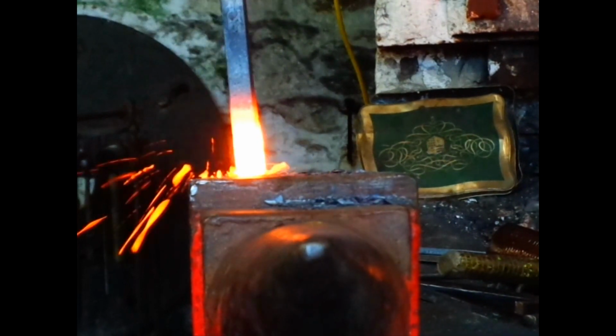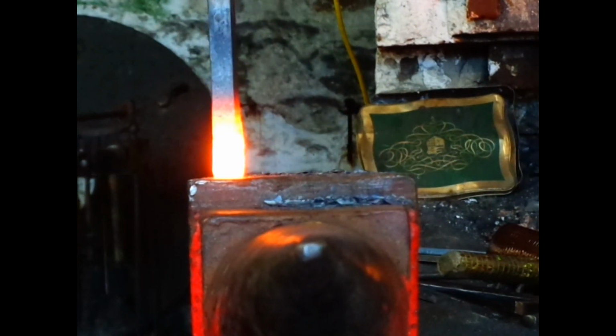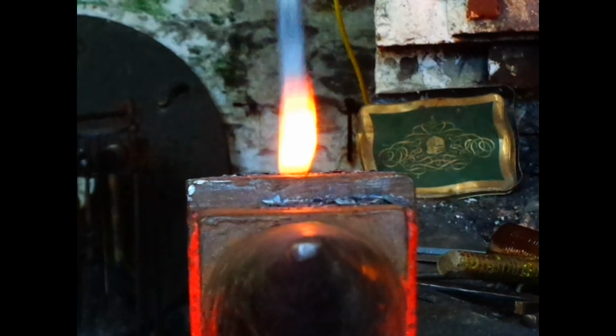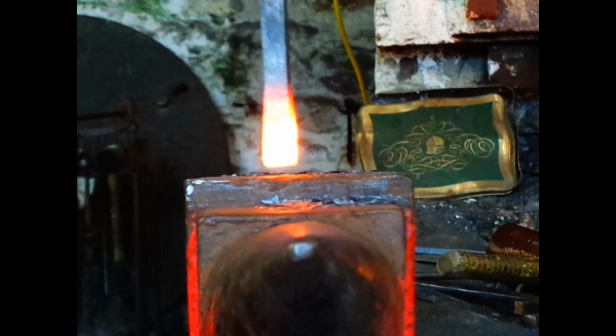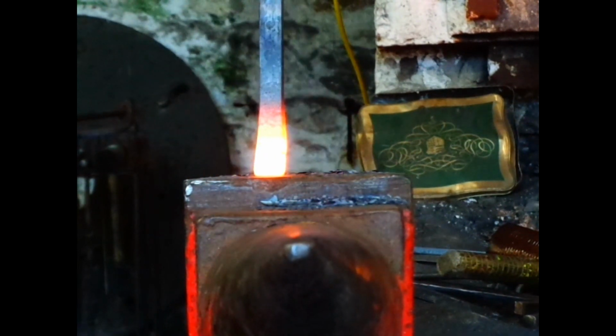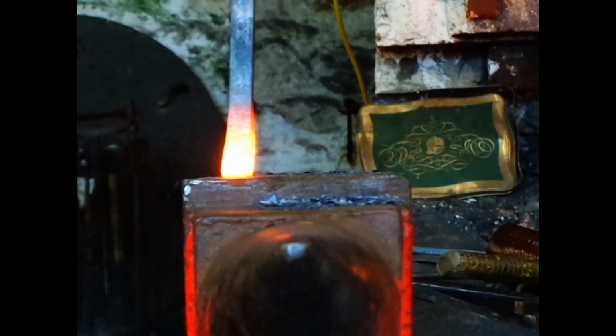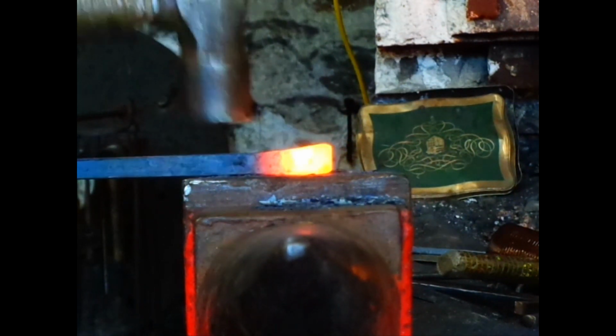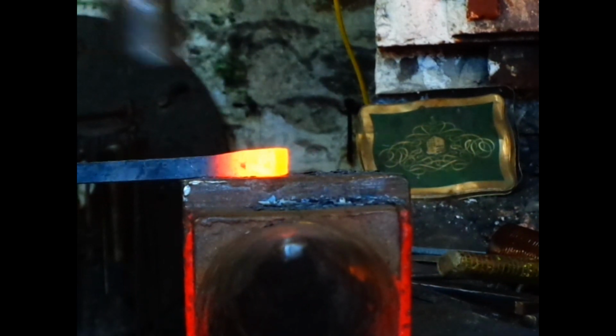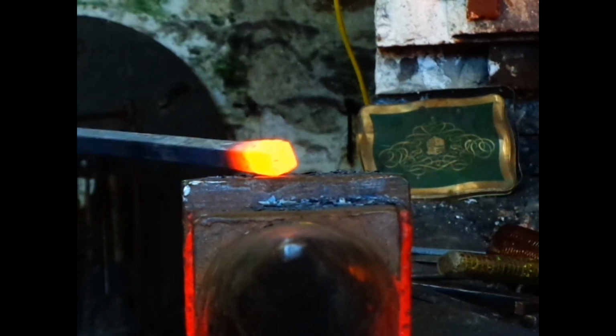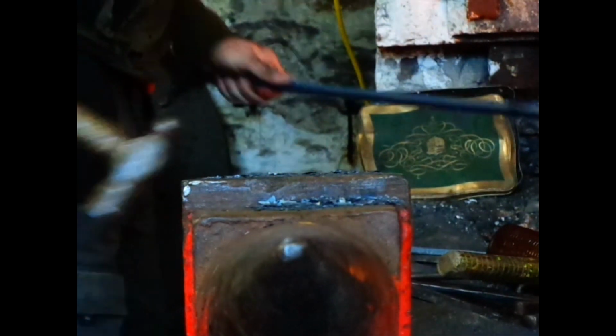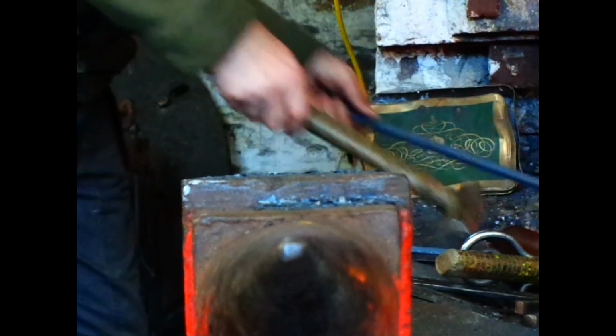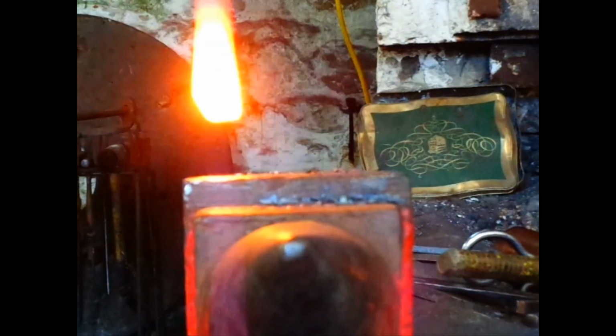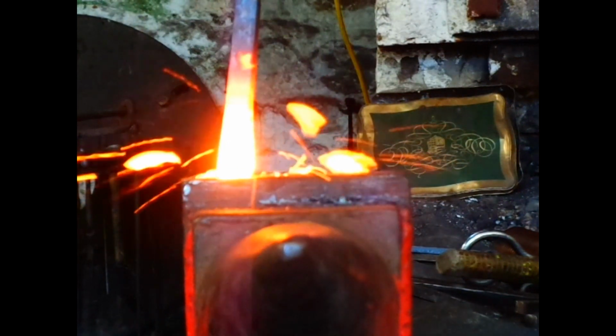Upsetting is pushing the metal back on itself to make the hot end fatter as it converts length into thickness. You need the extra thickness to prevent two things. The first is wastage. The longer a piece of metal is held at a high temperature, the more of it you lose through oxidization. The second is overforging. You need to forge the scarf joint heavily to ensure a good weld. If the parent bar isn't thick enough, you'll end up thinning it below its original section.